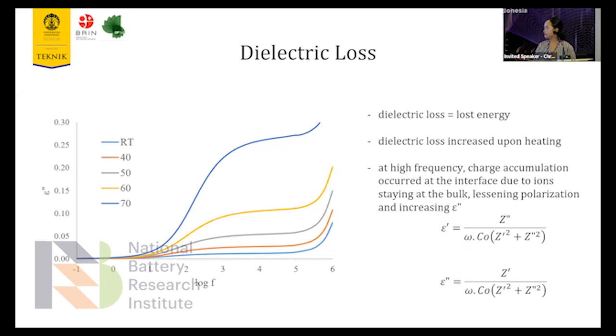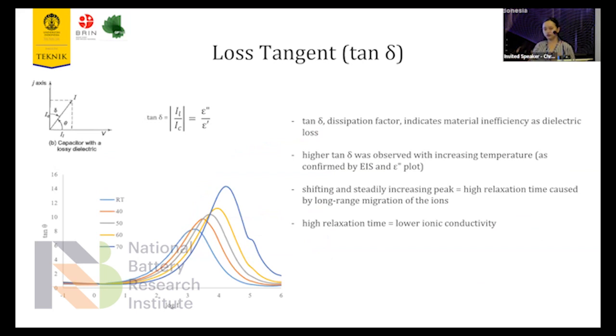And we further analyze it using loss tangent. And this is also the indication of how material is efficient or inefficient as dielectric materials. And we can see here at the curve that from the room temperature to 40, 50, 60, and 70, the curve is steadily shifting and even increasing. The higher tan delta, which is inversely proportional to the dielectric loss, was observed with increasing temperature. This is also confirmed by the impedance before at the Nyquist plot and ionic conductivity and the dielectric loss plot. So it is confirmed by previous analysis.